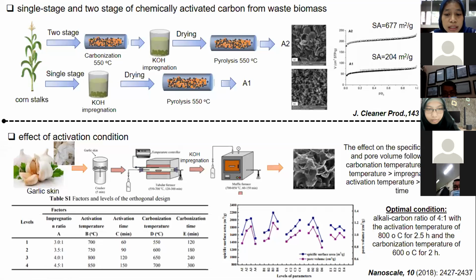For a single stage process, the granular powder of cornstalk was mixed with KOH solution, followed by pyrolysis process in nitrogen atmosphere at 550 degrees Celsius. And after washing this product, they obtained A1 sample. Well, for the two-stage pyrolysis process, the granular powder of cornstalk was firstly pyrolyzed in nitrogen atmosphere at 550 degrees Celsius. After that, the obtained char was impregnated with KOH solution, followed by second pyrolysis process at the same temperature. After washing this, the sample A2 was obtained.